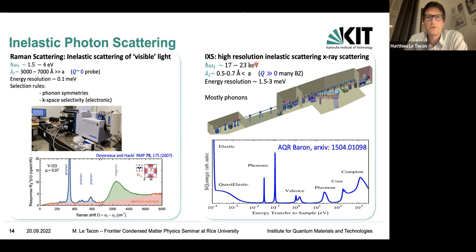at a synchrotron radiation facility. So here's a scheme of the beamline ID28 at the ESRF. That's basically a very long spectrometer. I'm not going to enter the detail. What we get is typically an energy resolution of 1.5 to 3 milli-electron volt, so it's not as good as for the Raman scattering. But the big advantage is that because of the short wavelengths, we can cover many Brillouin zones. And this gives us some selection rules, some contrast between the different Brillouin zones